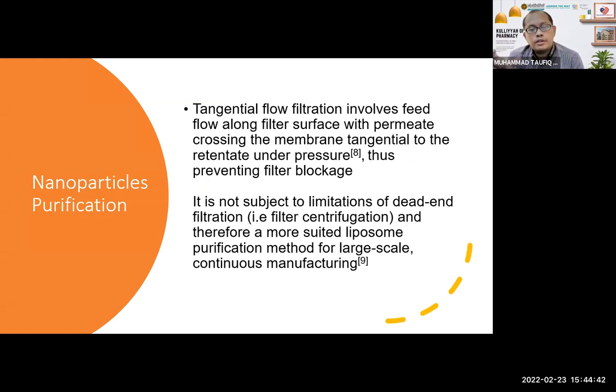So we come to tangential flow filtration. Basically, what you do is that instead of passing the fluid directly, following the flow of the solution, we make sure that the filtrate passes tangential to the flow of the solution. This is using pressure as well, but the pressure is very low compared to what we experience with filter centrifugation.